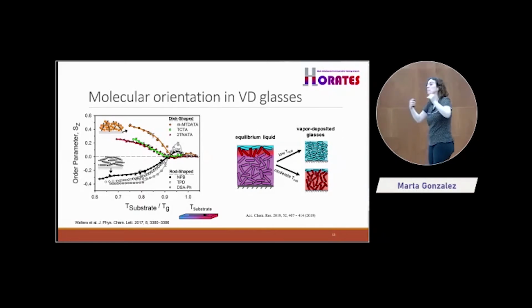So what's happening when we deposit our films? When we deposit our films, if we go to very low temperatures, we are in this region here. We are not providing the system time and energy enough to equilibrate, so we are depositing the whole system like this. If we go to a slightly higher temperature, the system has some time to equilibrate, but it only gets to here. We have to provide the system a lot of time and a lot of energy to be like this. And that's why all this region here corresponds to this kind of behavior. This is the reason.